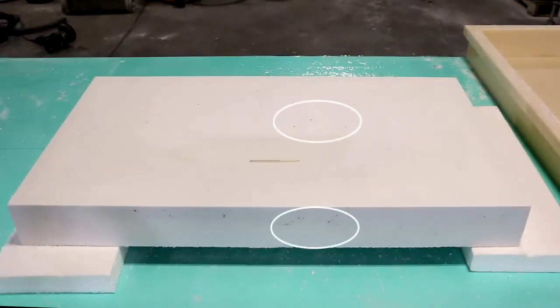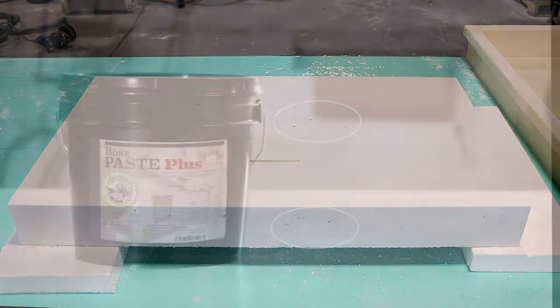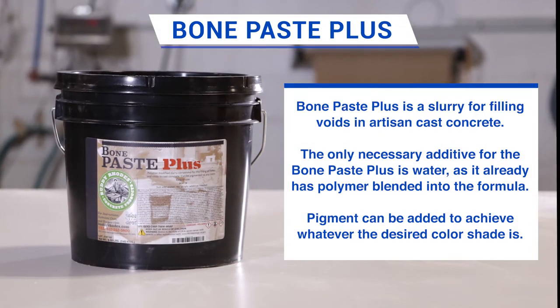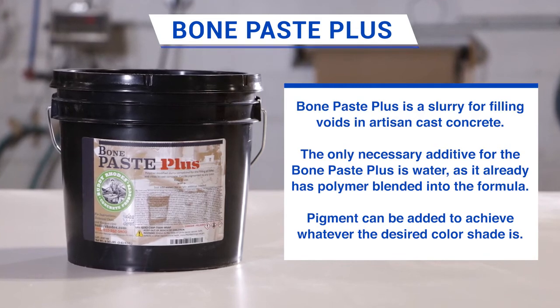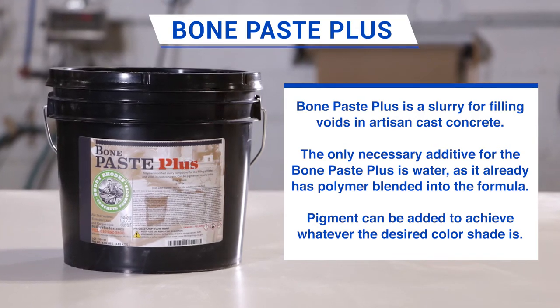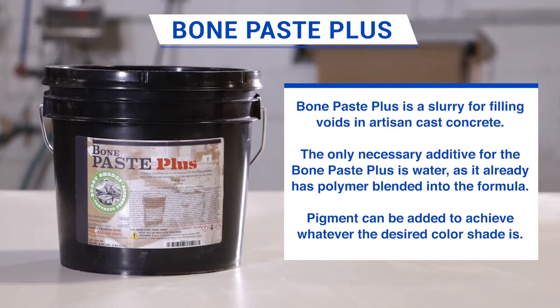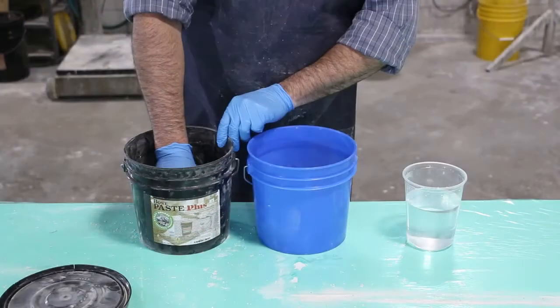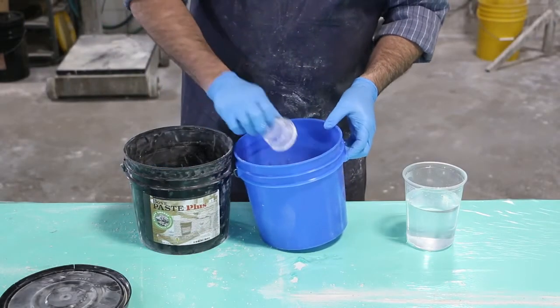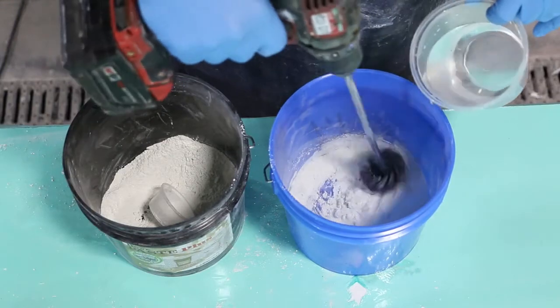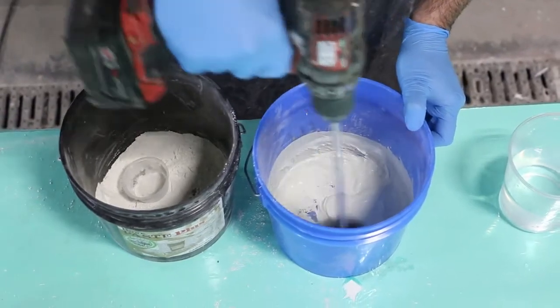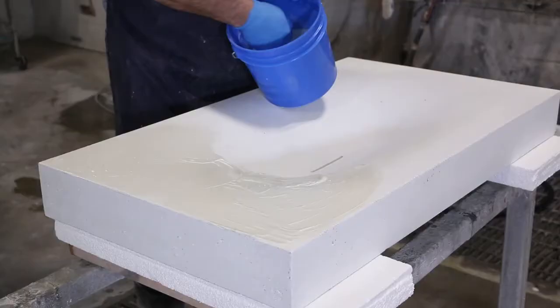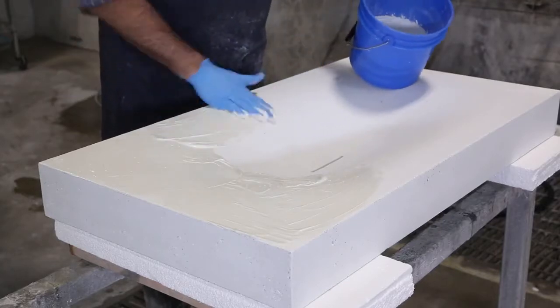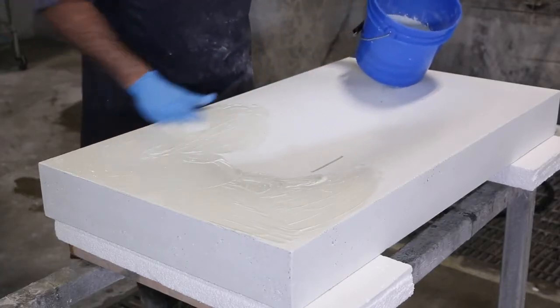As you can see, there are small random voids present, and these need to be filled flush with the surface. These can easily be filled with the Buddy Rhodes bone paste. For this project, I chose to use the natural color, bone white, to complement the white cast piece. Once the casting is dry, I mix bone paste with water to a creamy consistency and apply to all surfaces, applying in a circular hand motion to ensure I fill any voids present.